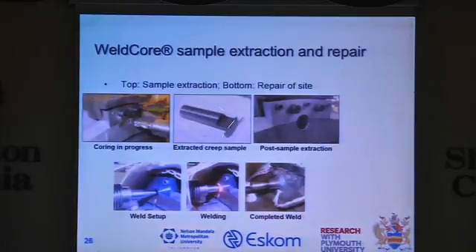It's a coring stage, you get the core out. Now from taking the core out of the turbine, within 4 to 5 hours we have the answer from the metallurgist saying whether this is creep damage, the turbine must be reworked, the turbine must be scrapped, or it can go back into service. So the total process, including the longest part, your pre and post-weld treatment, is within 2 days. Within 2 days we can get a decision whether the turbine can go back into service or not.